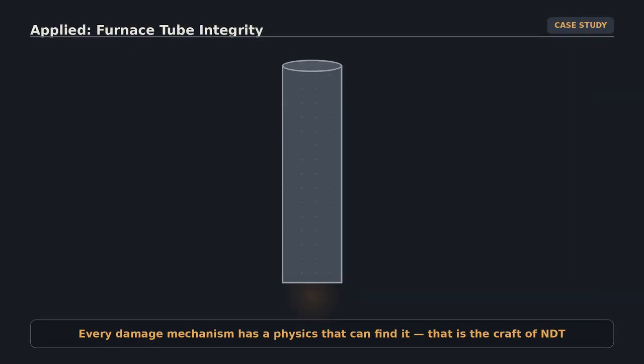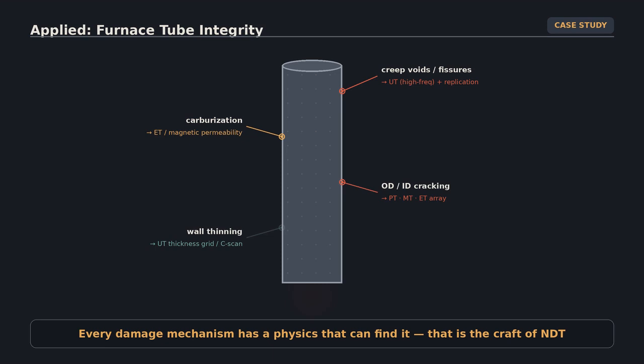In the fired heater, every damage mechanism has a physics that finds it. Creep, ultrasonics and replication. Carburization, eddy current. Cracking, PT, MT, arrays. Thinning, a UT grid. Bowing, laser profiling. Then the data feeds API 530 and 579. Inspect, detect, predict.